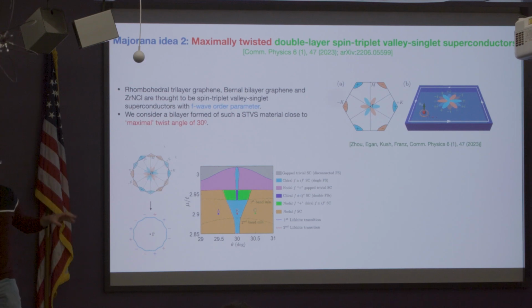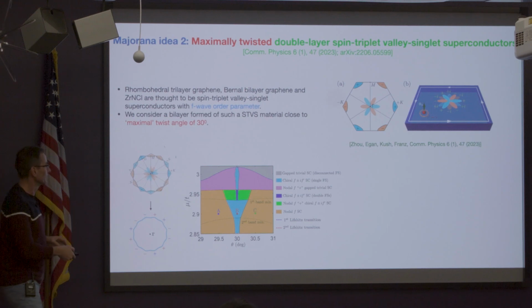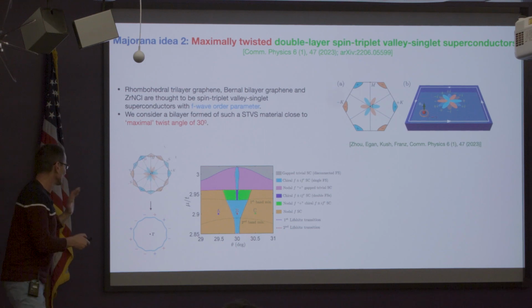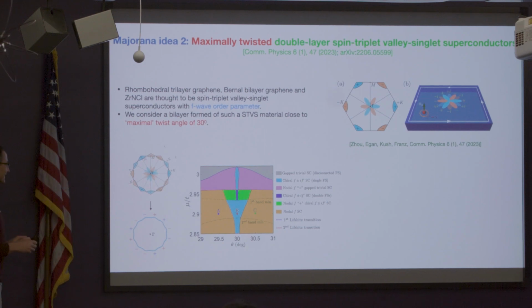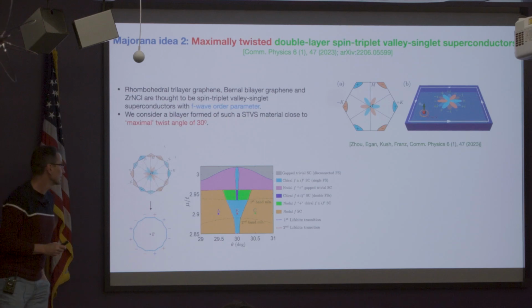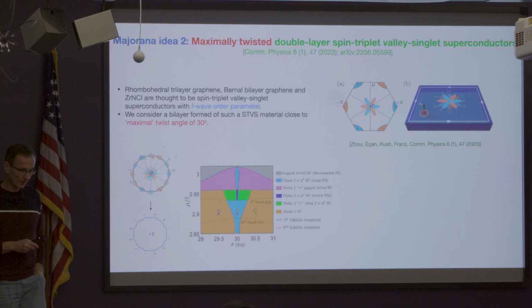Of course, in our case, we're not only interested in the normal state, we're interested in the superconducting state. So this was quite a tour de force that Benjamin and my 2 students went through. But I think this is a correct result of that calculation. We ran lots of checks and balances, and it all made sense. So, to the extent that we can trust this phase diagram, there is a significant part of it where there is this interesting chiral F plus iF prime phase.